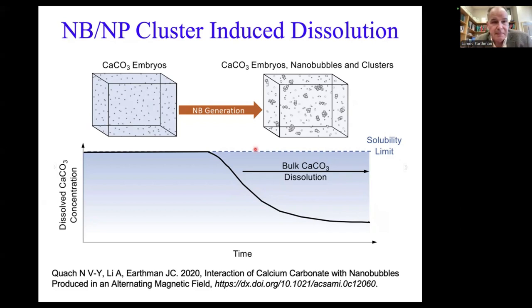You've got something at the solubility limit. That's typically where you're going to be in one of these surface water systems, because if there's more calcium carbonate in the water, it's going to deposit somewhere, and the concentration will go back down to the solubility limit. If there's not enough calcium carbonate in the water, then something will dissolve. The calcium carbonate will dissolve somewhere and bring the concentration back up. So you're typically around the solubility limit of that compound in the water when you have it depositing on the pipes, when it's fouling. If you add nanobubbles, you're going to form clusters.